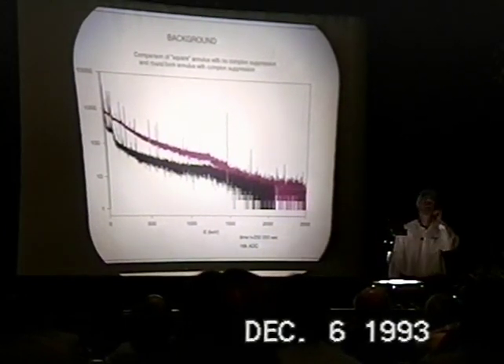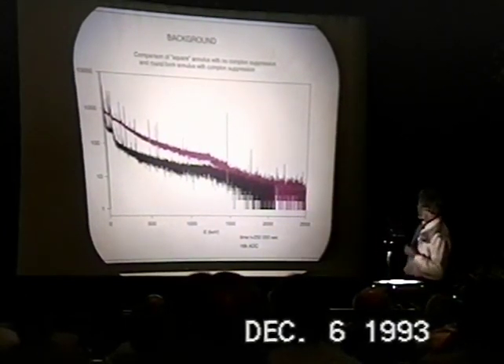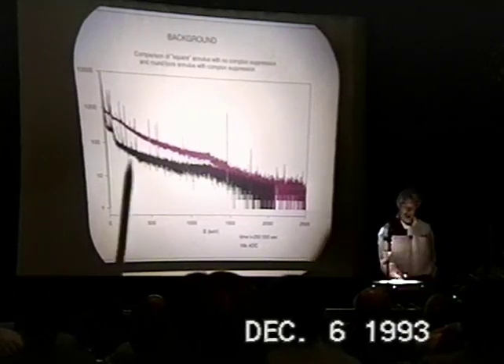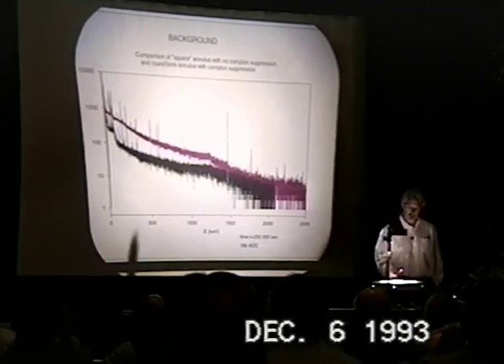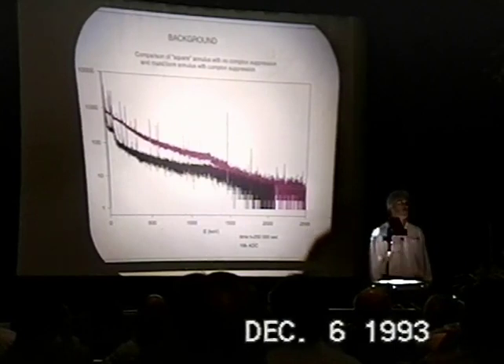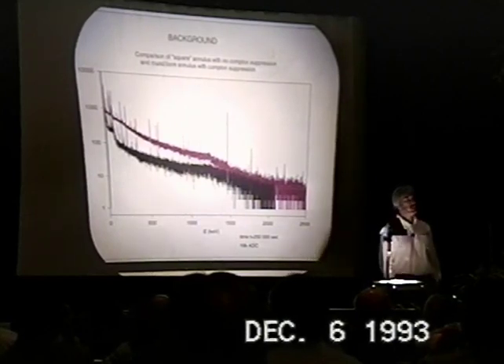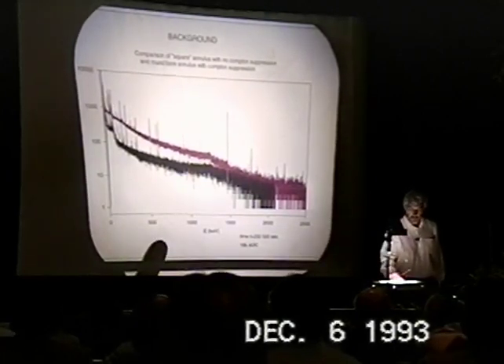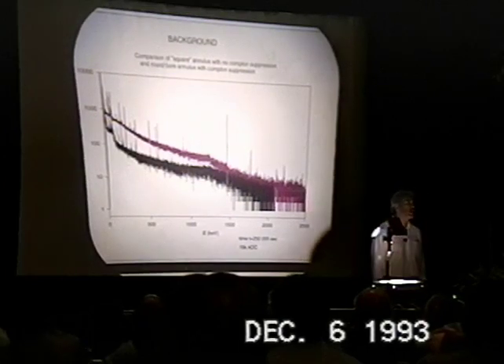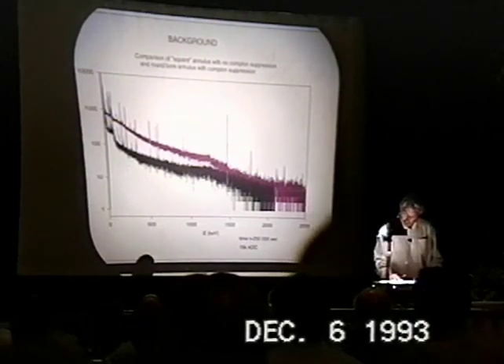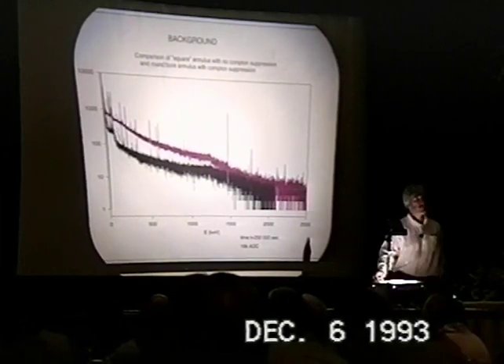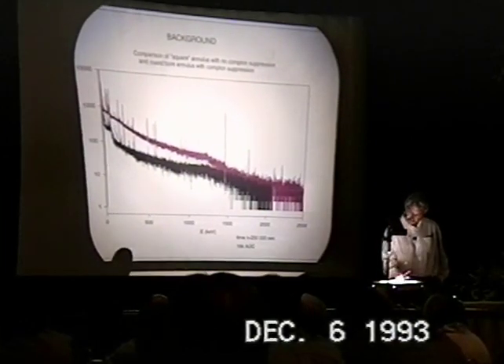This is a slide that Nada prepared for me. It took her about a day and I have to present it. The red is the background without Compton suppression. The black is the background with Compton suppression. Basically, our background is 1 count per second in the range of 3 keV to whatever we've got it out to here, probably 2 or 3 MeV.